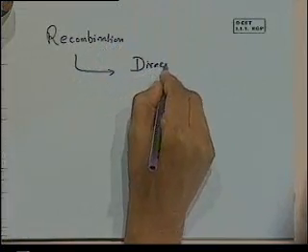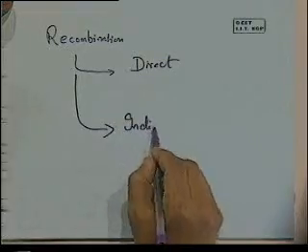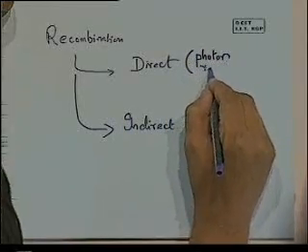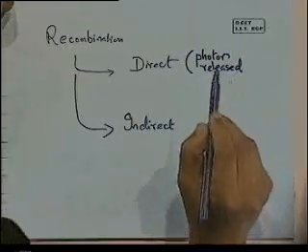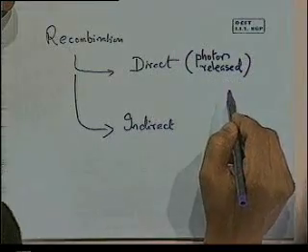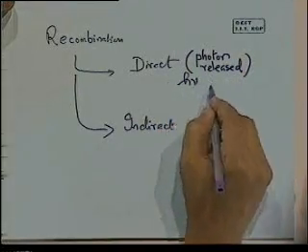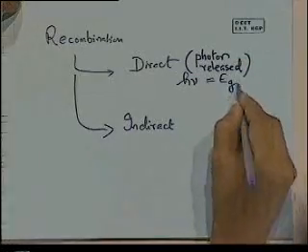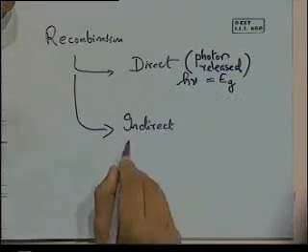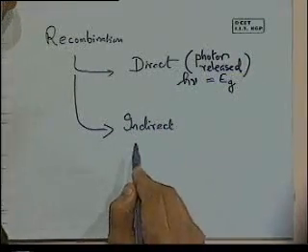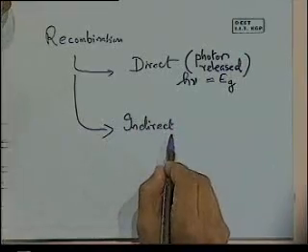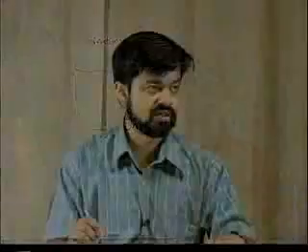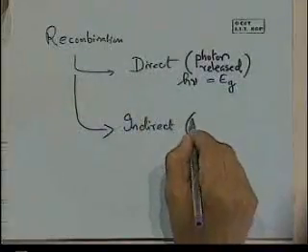Recombination can occur in two ways: direct recombination and indirect recombination. In direct recombination, typically a photon is released as the electron moves from the conduction band back into the valence band, and the photon has an energy h·nu roughly equal to E_g. In indirect recombination, the process of directly going from the conduction band to the valence band is not very efficient and phonons are involved.